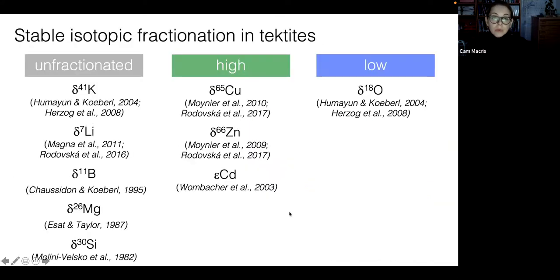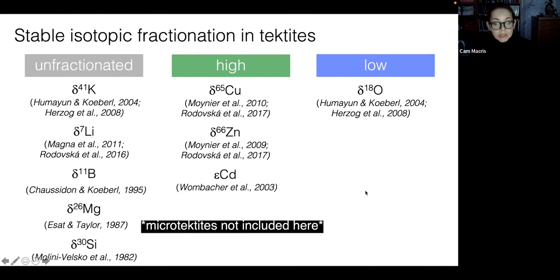But if we look at an overview of stable isotope fractionation behavior in tektites, it's not really straightforward at first glance. On the left here, we see a list of isotope systems that appear to be unfractionated in tektites relative to their protoliths or parent materials. In the middle are systems that are higher, including copper and zinc. And on the right, we have oxygen, which is lower in tektites than in the proposed parent material. These lists do not include data from microtektites, for which there is limited data indicating both heavy, light, and unfractionated samples for potassium and iron.